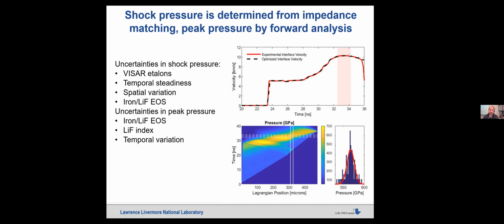So by matching this hydrocode output, we can then obtain the histogram of pressure and density states at the time of the X-ray diffraction, where we have our X-ray sources on for about a nanosecond. And so we can obtain the time integrated pressure states during the time of our X-ray diffraction. And because of the pulse shaping capabilities again, we get a very narrow pressure distribution. So we have a pretty small uncertainty in the pressure in the peak states.